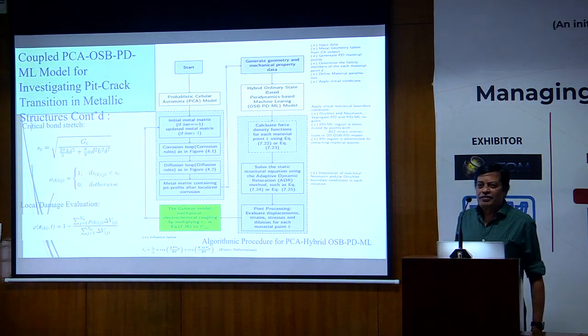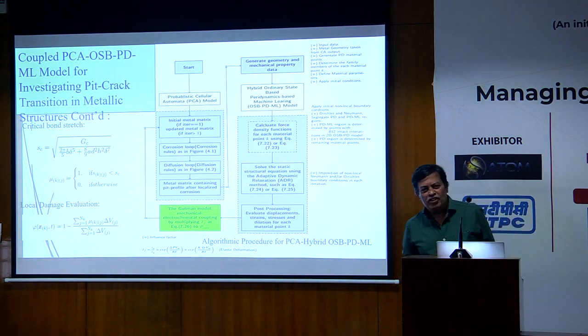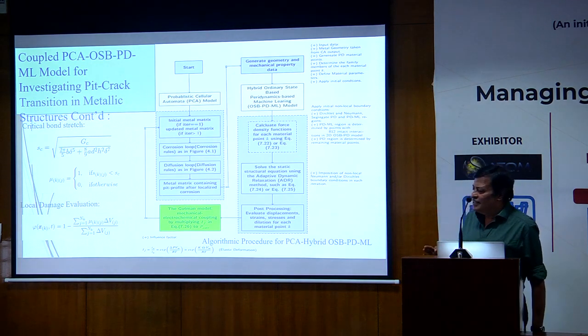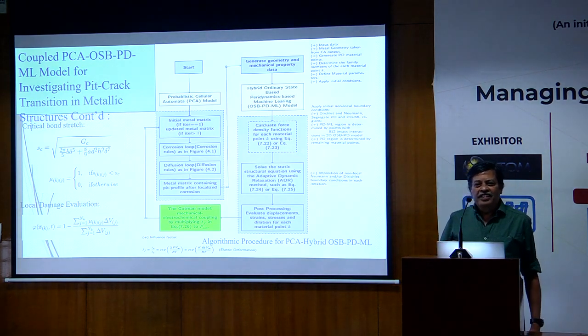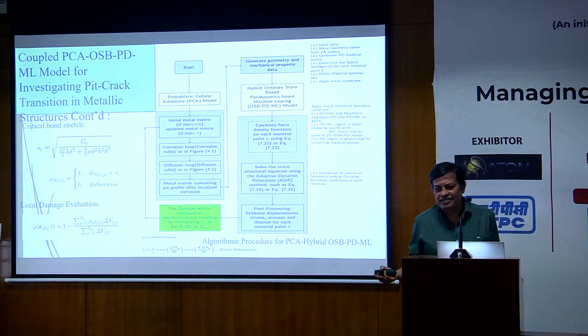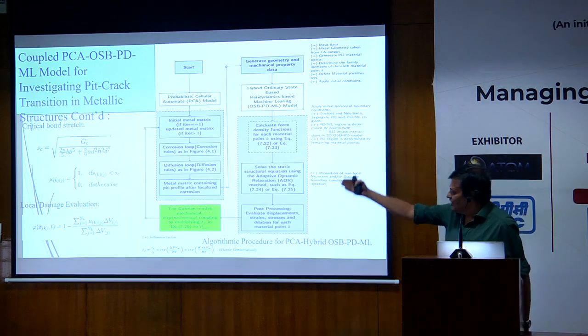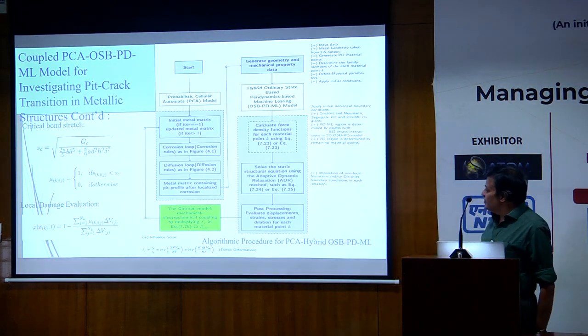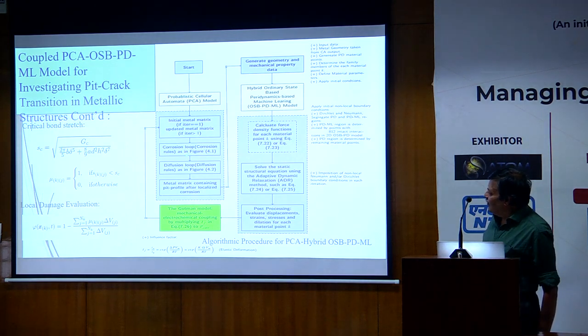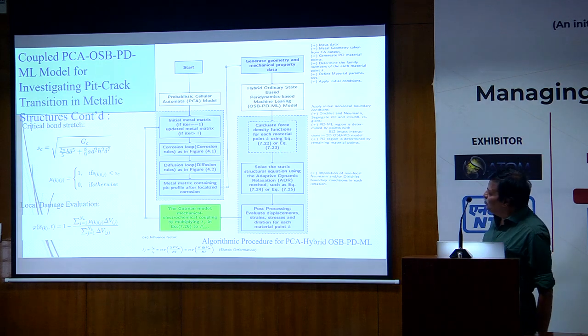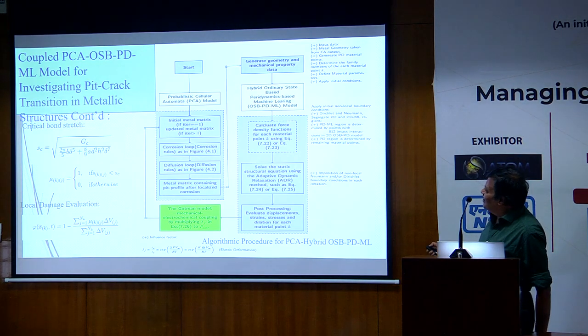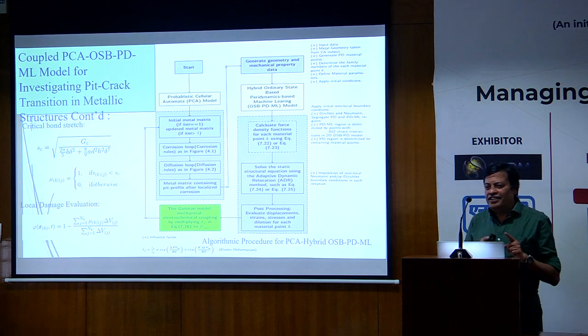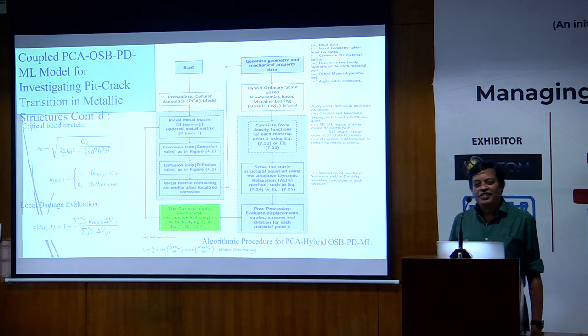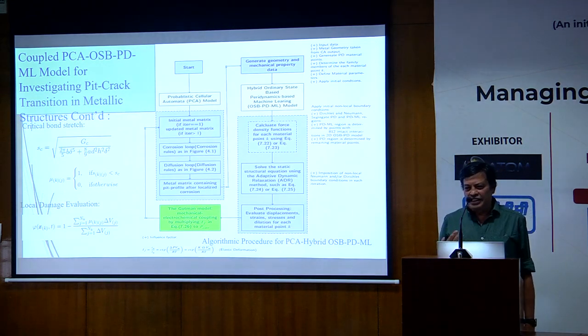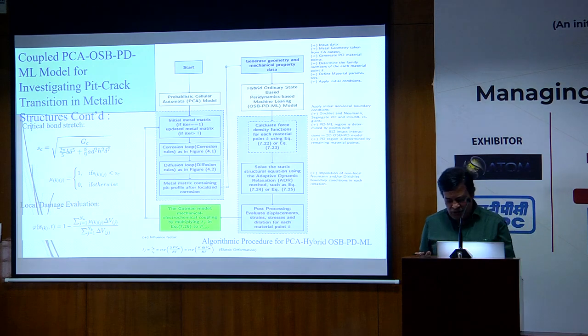And this is the last approach, where we used the probabilistic cellular automata and the bond-based peridynamics machine learning model together. The idea here is this model can predict pit-to-crack transition, just the way PCA did. And this is the whole solution process, the flow chart. So you have a corrosion loop, a diffusion loop, the same kind of probability we assume. We use a Gutmann relation. And instead of the XFEM solution, we replaced it with the peridynamics machine learning solution. So the idea here is this model is 5 times more computationally efficient, and it requires much less memory so that you can get fast solutions.